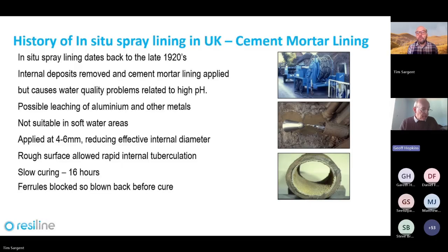encrustation and degradation. The problem is if you just clean iron metallic pipes, within a matter of weeks, you finish up with what was always called red water. You get a rapid reformation of soft internal deposits that run about inside the distribution network, giving everybody discoloured water. So you can't just clean them, you have to clean them and you have to apply a sealing coating as well.